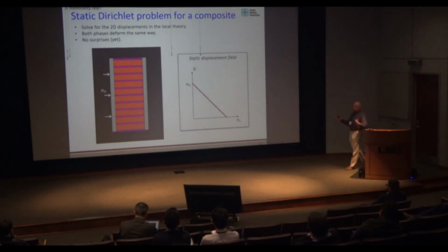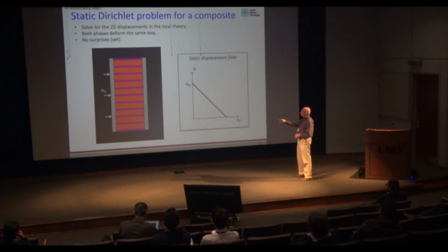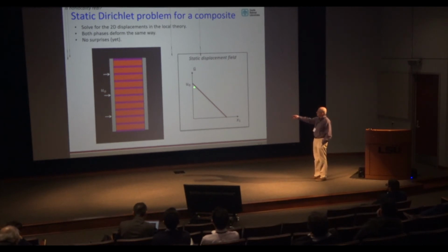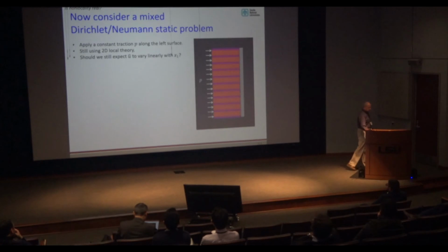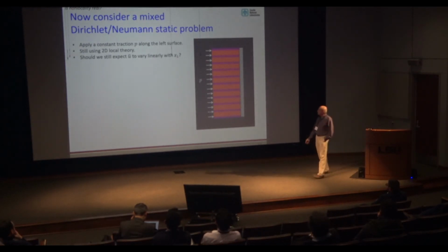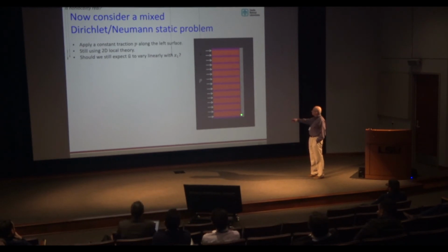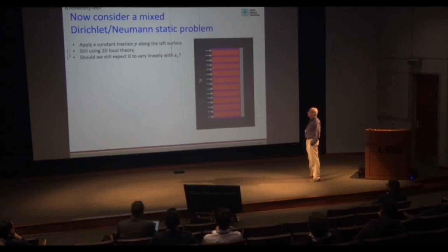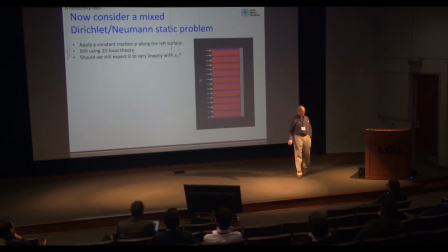Now, if you take two plates located on opposite sides of this composite and just compress the plates together, then lo and behold, you get a linear function of position for the average displacements along vertical lines. So no surprises there. However, suppose you change the problem a little bit, and we still have a rigid plate on the right side, but on the left side we prescribe constant traction along this surface. So individually on these alternating stripes, you have constant force per unit area applied. So should we expect the same result as in the Dirichlet problem?